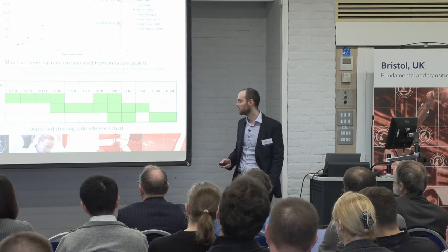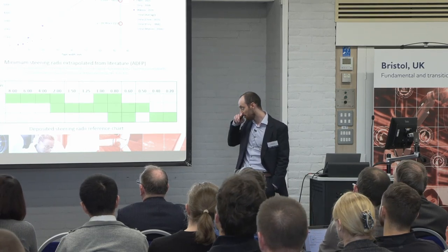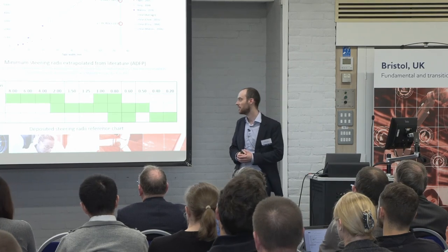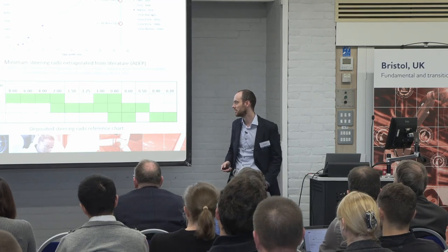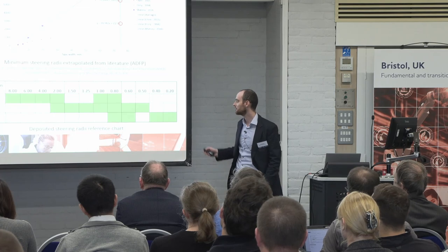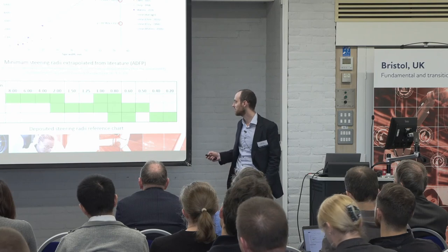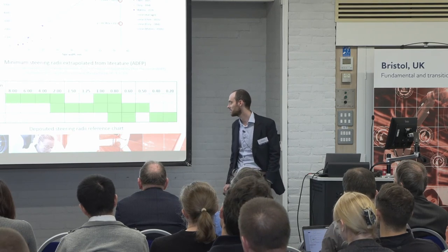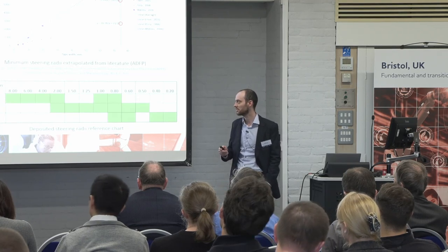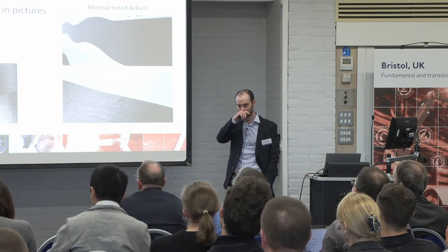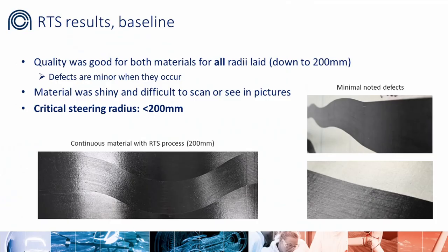So we came up with a rosette, or an array of steering, for ATL. And then we're comparing it to previous results from AFP, which is much thinner width, higher steering capability, but with the higher cost associated. And also, very importantly, demonstrate the rapid tow shearing process. And again, we're crossing everything over at a 0.8 meter radius, but the rapid tow shearing, based on ICOMAT's experience, we're expecting to go much, much lower, down to 200 mm, which is a really tight corner for this type of material.